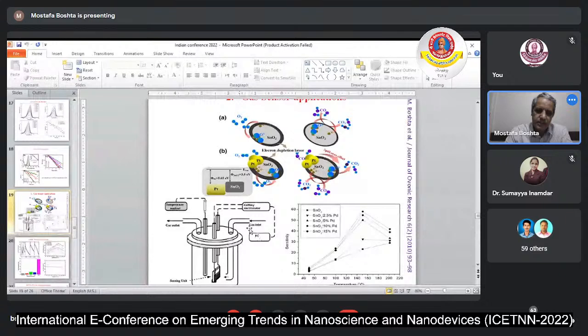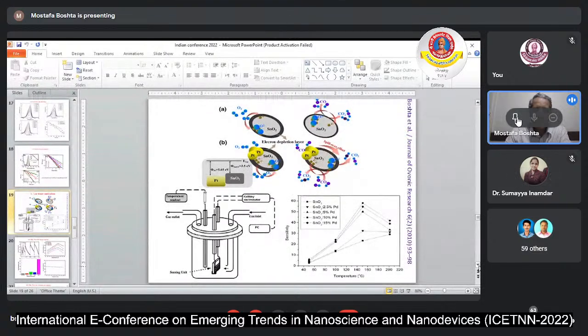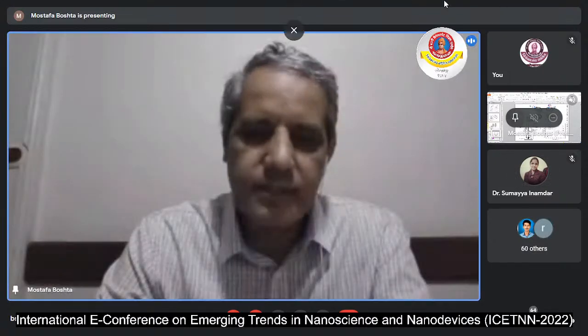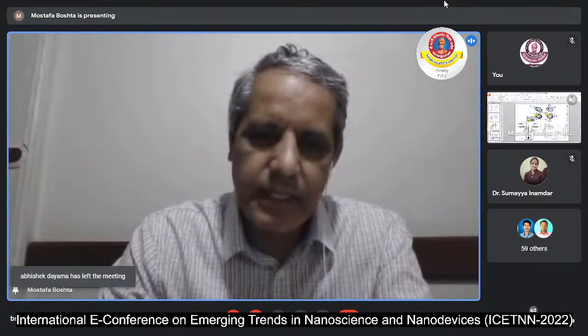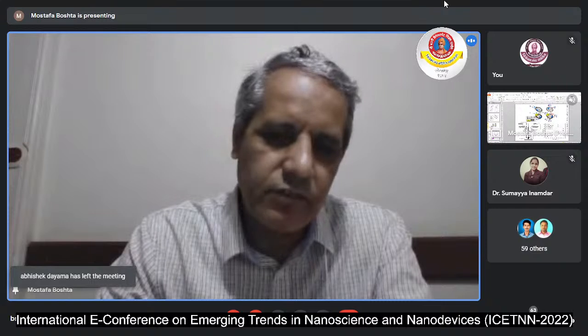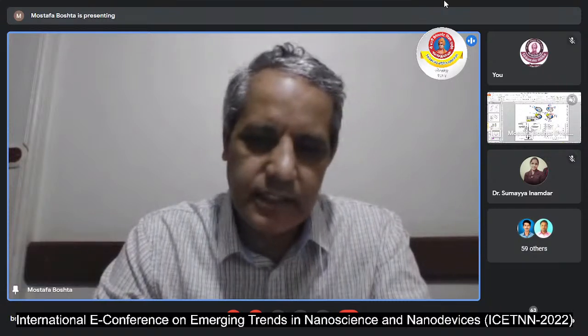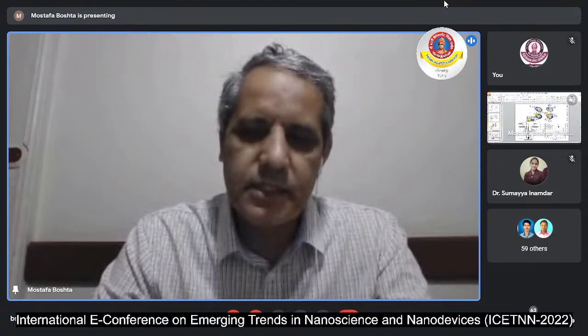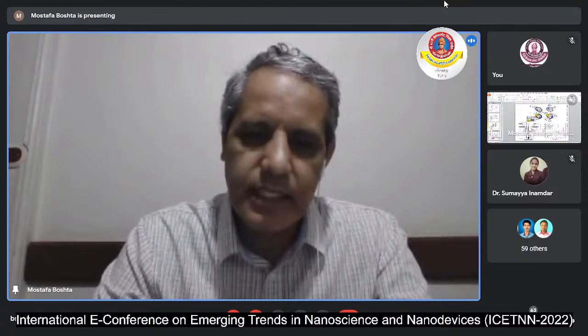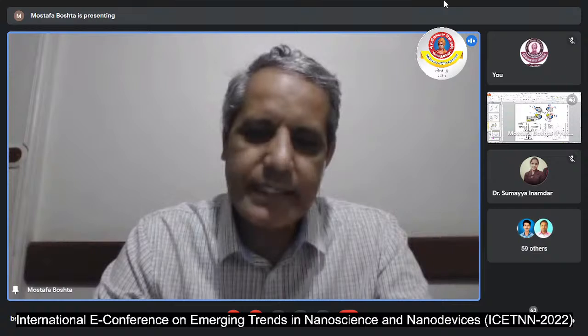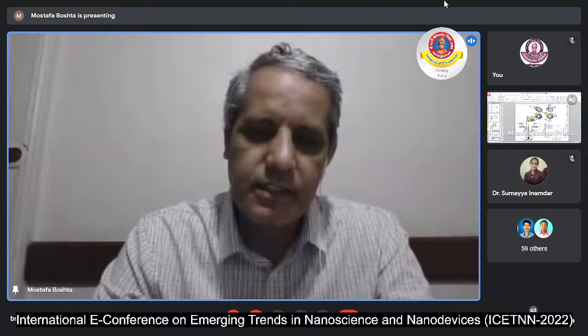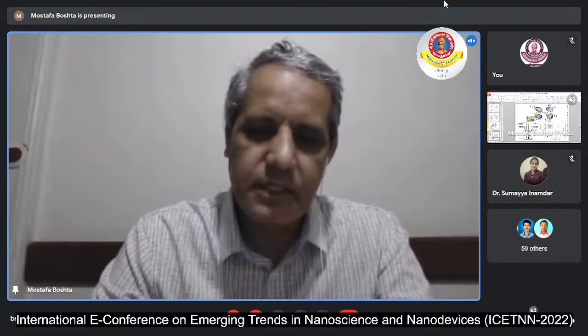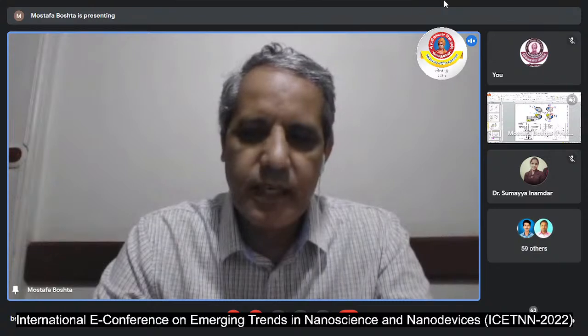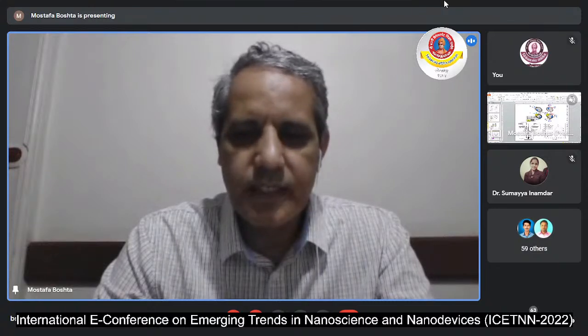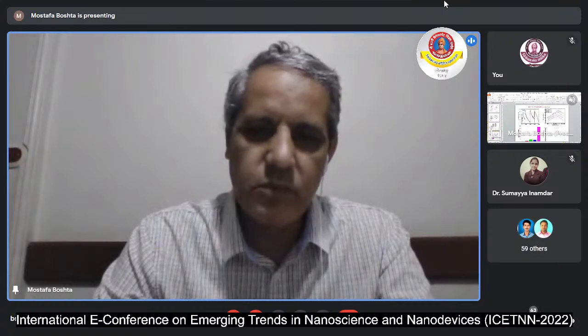We use this technique for measurement of the gas sensor material for carbon monoxide. As we can see, when we add palladium to the tin oxide material, the efficiency of the gas sensor is increased. Also, this material can sense the polluted carbon monoxide at a low temperature, about 150 degrees. It is a low temperature for this material, and we can measure the gas pollution and know that carbon monoxide exists in the area which we live in.